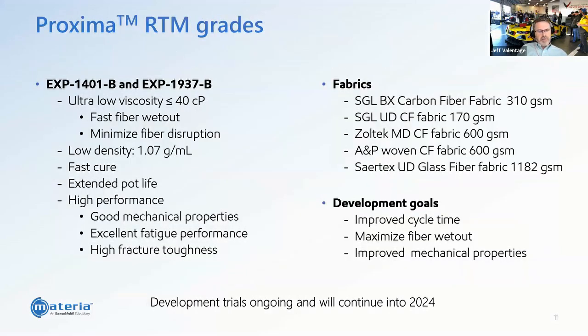And then lastly, just to talk about the grades that we've chosen for this particular development. The two grades that we have today that we're working with are EXP 1401B and 1937B. These were chosen because of their ultra low viscosity, 40 centipoise or below. And really that's for two reasons, because we want to make sure we get very fast fiber wet out, like I showed you in the video with the infusion of the wind turbine blade. We want to be able to wet out those fibers uniformly across the part, but also minimize fiber disruption. So that's a key area that we're looking at.